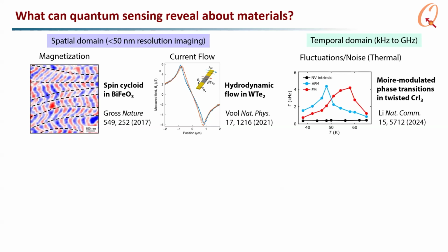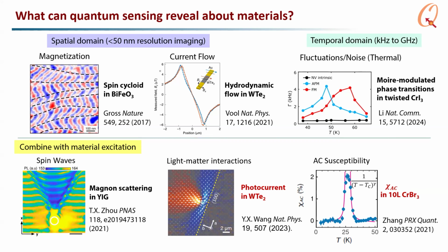Okay, but what can quantum sensing reveal about materials? So today I'll go over sort of two main applications. One is in the spatial domain, which is imaging magnetization and current flow through the Ørsted field at sub 50 nanometer resolution. And one is to measure essentially fluctuations or noise in the temporal domain. But you can also combine all of these modalities with material excitation. For example, you can drive spin waves in a ferromagnetic insulator. You can also drive photocurrents, and then you can also excite the material with AC magnetic fields to measure AC susceptibility, as we did in our lab.